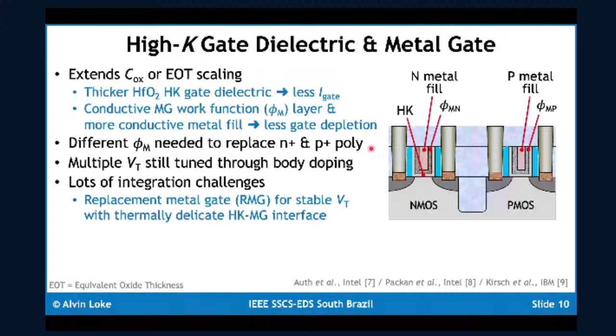So the industry solved this problem by migrating to a replacement metal gate process, where you build your gates using polysilicon until the very back end, do the source drain anneals first, and then after the anneal and subsequent contact dielectric deposition and back polish down to expose the top of the gate, you rip out the polysilicon gate, and in a Damascene atomic layer deposition process, you deposit your HighK dielectric and the various layers of your metal gate, then subsequently polish away to inlay the metal gate.